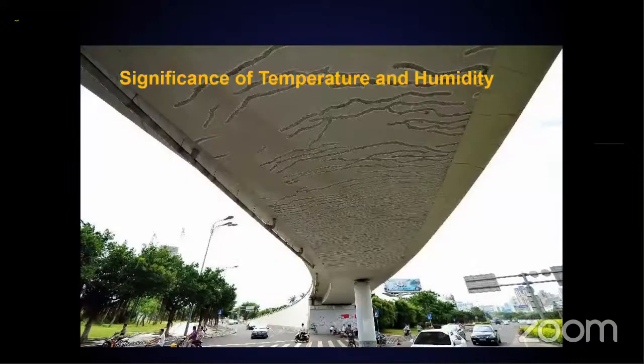But there was a huge investigation that was done. It was found that because of the relative humidity and temperature, the shrinkage strains changed. They concluded that the humidity effect on shrinkage is the primary cause for these cracks. That is, when the temperature rises, the moisture in the concrete diffuses more rapidly as humidity descends, which results in larger concrete shrinkage. This was the conclusion provided.